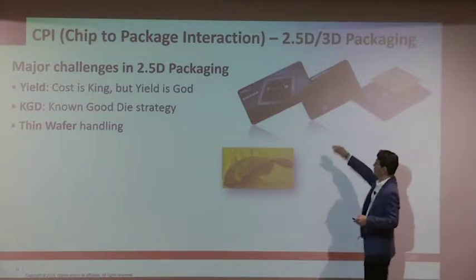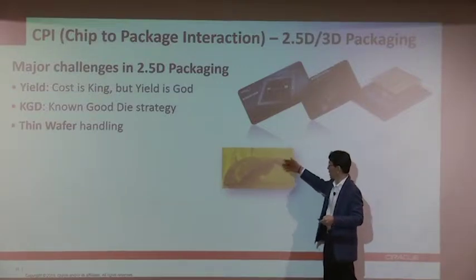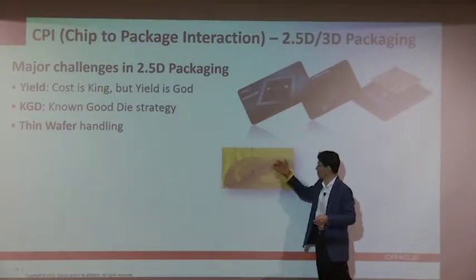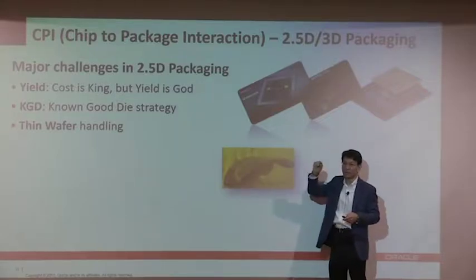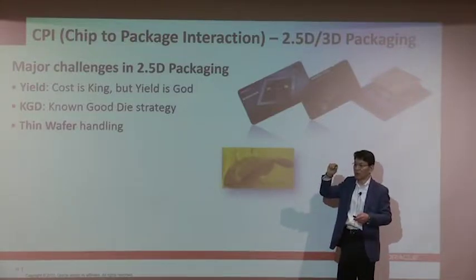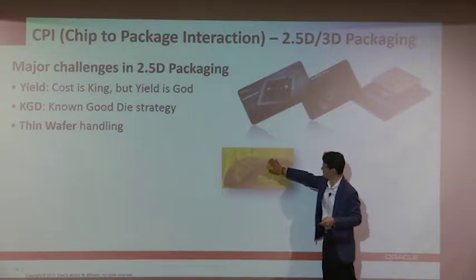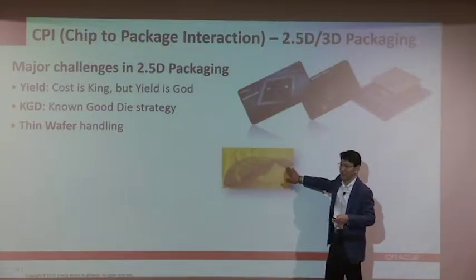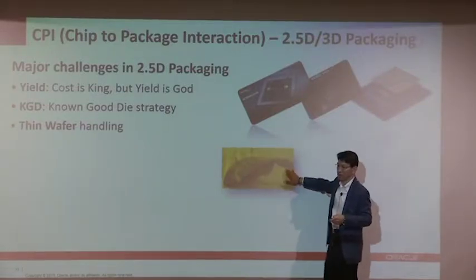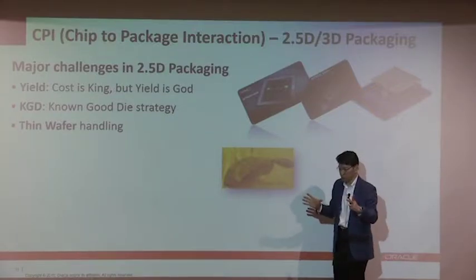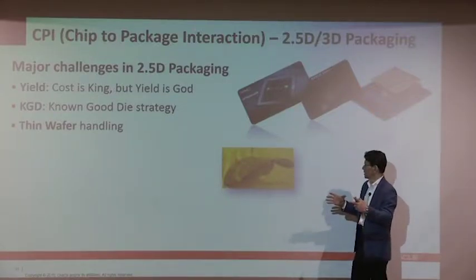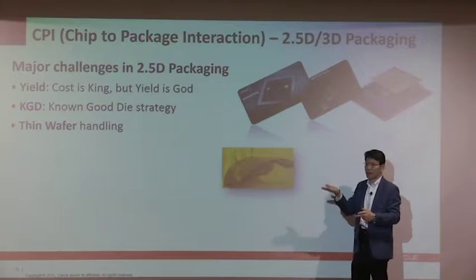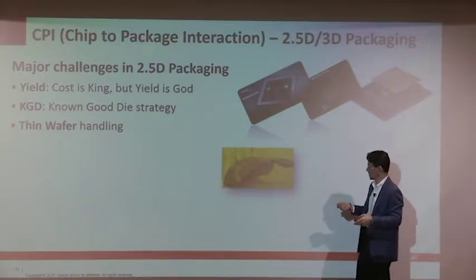And having that 2.5D package, the interposer always goes very thin, like 50 micron or 100 micron thin. So it is not A4 paper. It is real wafers, thinned, 12 inches, 300 millimeter. Weaker than real paper.